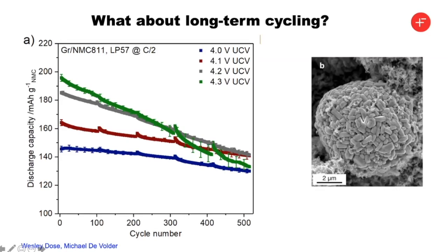you can see that when you cycle at low voltages, so 4 volts and 4.1 volts, we're getting very respectable capacity retention. But once you go above 4.2 and 4.3 volts, although you get some good initial capacity, it drops off very rapidly. And these are cycling data from Wes Dose in Cambridge.